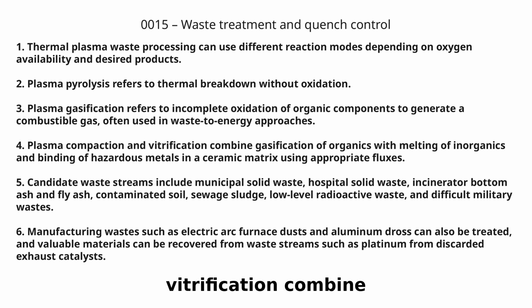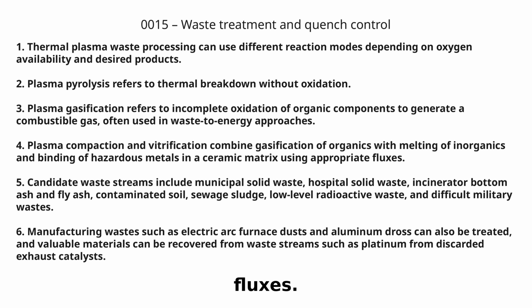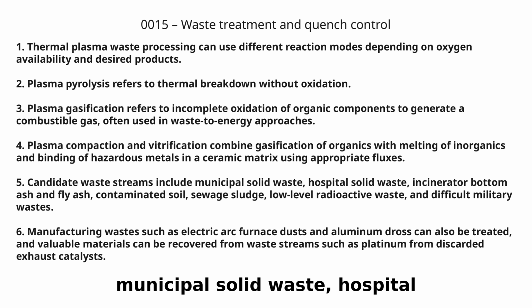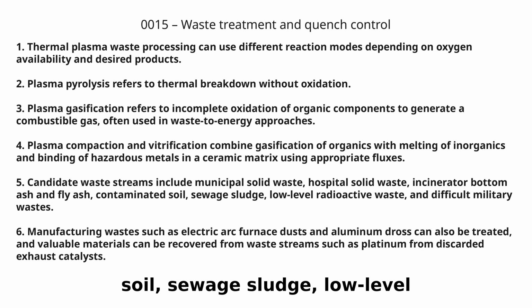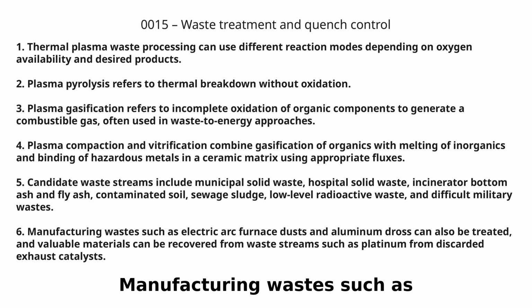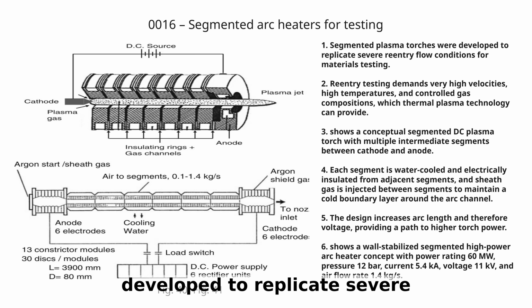Plasma compaction and vitrification combine gasification of organics with melting of inorganics and binding of hazardous metals in a ceramic matrix using appropriate fluxes. Candidate waste streams include municipal solid waste, hospital solid waste, incinerator bottom ash and fly ash, contaminated soil, sewage sludge, low-level radioactive waste, and difficult military wastes. Manufacturing wastes such as electric arc furnace dusts and aluminum dross can also be treated, and valuable materials can be recovered from waste streams, such as platinum from discarded exhaust catalysts. Segmented plasma torches were developed to replicate severe reentry flow conditions for materials testing.